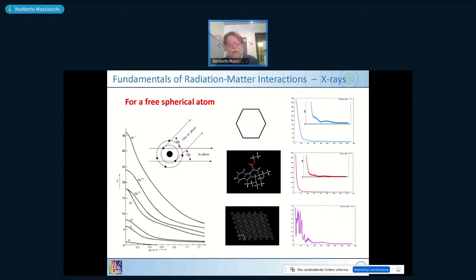So we are now in the 1930s, when the first wave functions were computed. And as you can see here, depending on the angle, here reported as sin theta over lambda, but it's basically a function of theta, the farther away from the zero angle, which is the direction of the incident beam, the less contribution you have.